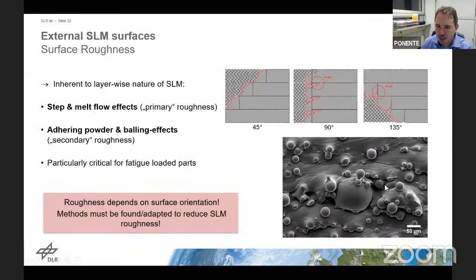You see here that there is, beside the melt effects, these melt shapes, a lot of powder particles attached to the surface. The typical SLM powder has an average diameter of, let's say, 40 microns, distribution between 10 and 60 or something. If you have a particle of 40 or 50 microns, your part has two sides. At each side, you have particles attached to the surface. Even if your melt tracks are going to end perfectly exactly on the geometry, which is already in this top image not the case, then you have attached particles. Two sides, 2 times 50 micrometers means your best accuracy that you can expect is plus minus 0.1 millimeters naturally.